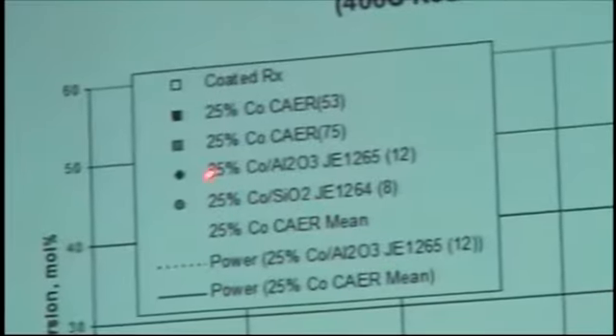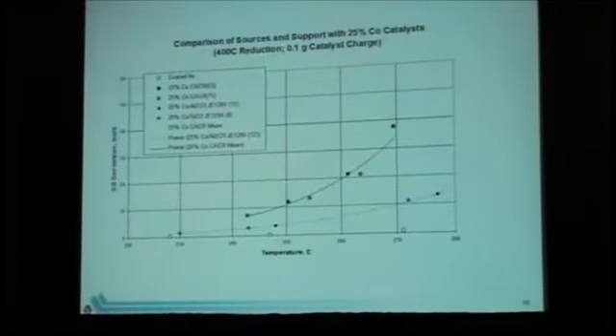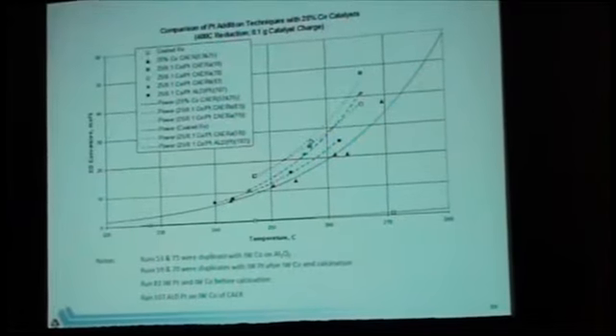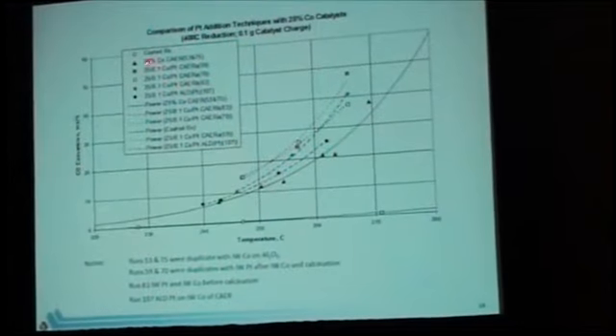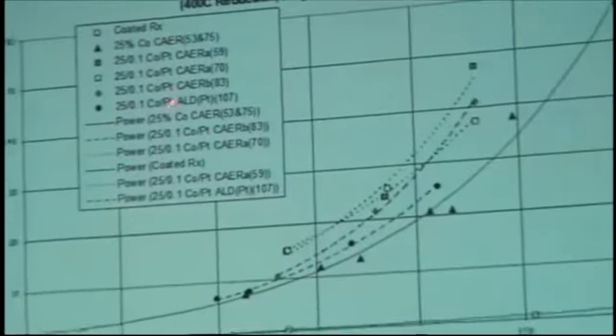Comparison of sources, again, a similar sort of, and let me pass by at this stage, I'm getting a little close on time. At various catalysts, looking at the 0.1% platinum, the 0.1% did not make a major difference in comparison to the 0.5%. These are shown purely to show that we're looking at an overlap within the error bar. Generally speaking, the catalysts need the temperature of the 450, but at the 0.1% platinum it is very strong in supporting the activity of the catalyst.